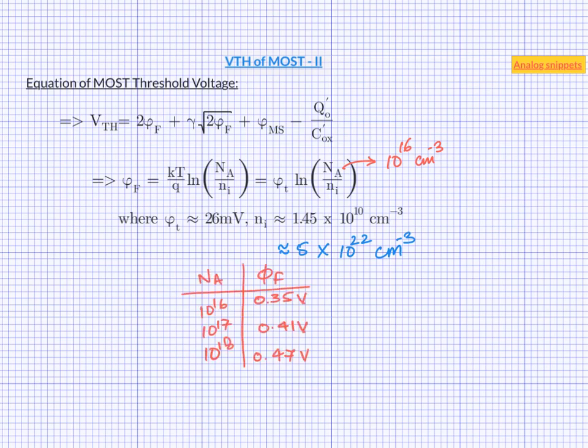Here we are. Now, substrate is rather lightly doped. So, the doping concentration would be around 10 to the power 16 to 10 to the power 17 per cubic centimeter. In following calculation, I would assume phi f to be around 0.4 volts.